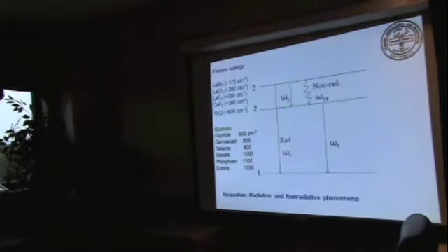So let's say this energy gap is around 2000 wave numbers. You excite that particular level with a laser beam, that means you transfer some electrons from here to here. So this electron, instead of jumping down and emitting radiation, if it is in something like sodium borate, doesn't relax radiatively, it just relaxes non-radiatively. That much energy it transfers to the host material. If it is a sodium borate material, the rare earth ion will transfer that much energy to the sodium borate. So that basically heats up the material. So that's called non-radiative relaxation.